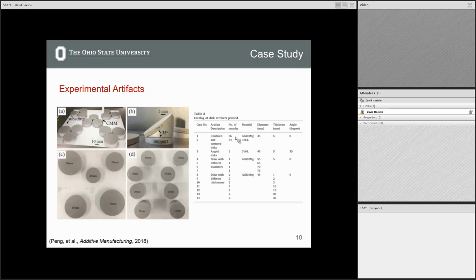The other thing that we did, that I'm not going to talk about in this presentation, is that we mostly printed them in this configuration, 15 on a single build plate. But we were also interested in whether there's variation in deformation if we just print one of them in the center. Actually a lot of these were a big waste of money, in that we would print just a single one in the middle, and that was it. We wanted to understand whether there is a difference in deformation and stress, and we found that there was not.